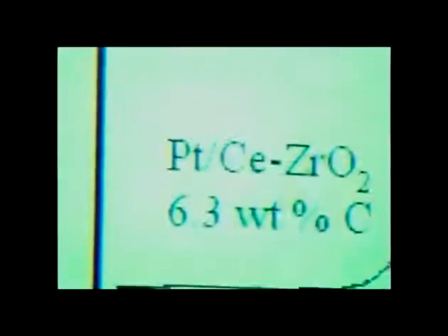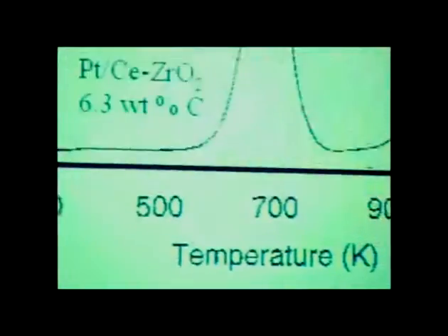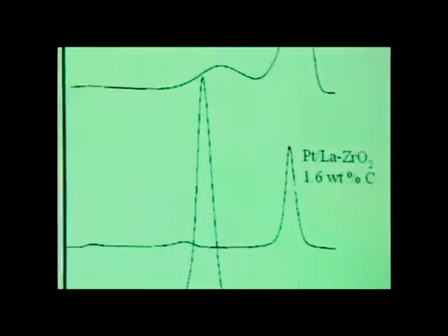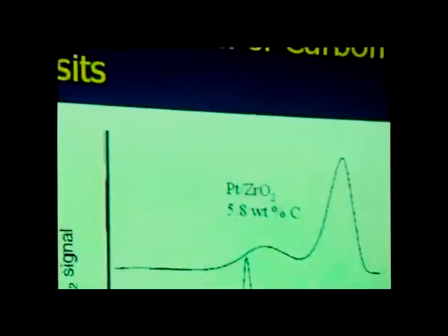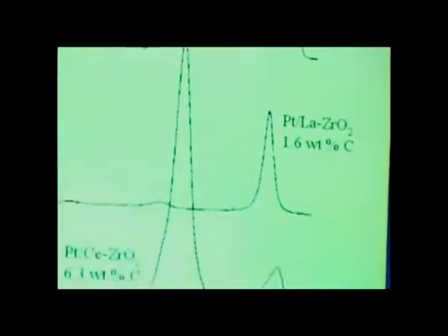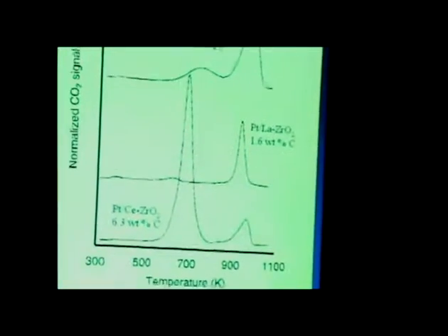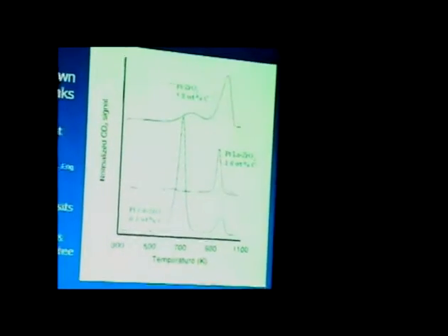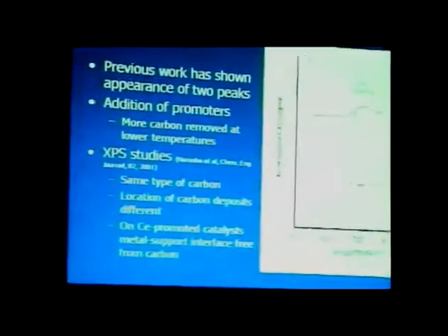Temperature programmed oxidation experiments have been done. Previous work has shown that on the ceria promoted material, you have similar amounts of carbon or slightly more carbon than on the zirconia by itself, but that the addition of the promoter moves the majority of that carbon to lower temperatures. And XPS studies have shown that it's the same type of carbon, but just the location of the carbon is different. On the ceria promoted catalyst, you virtually have a carbon-free metal support interface, where you may have carbon deposited in other places away from the metal.